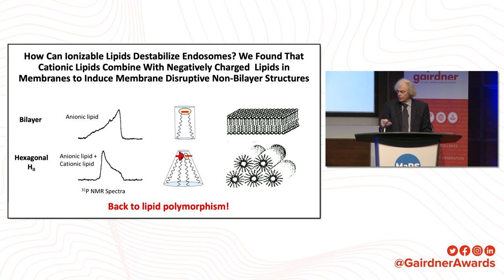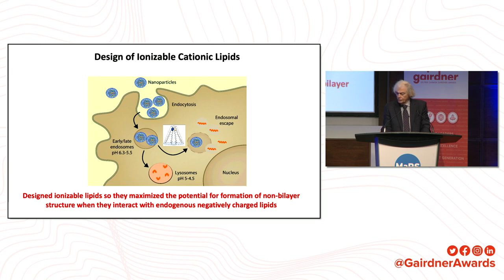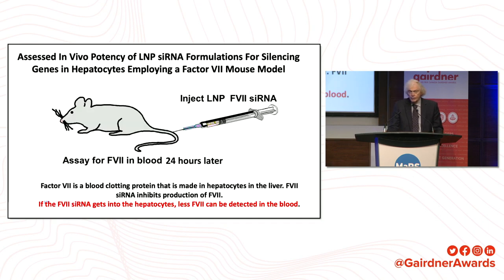And so this gave us a kind of design approach to go after the ionizable lipids, that at some point they become positively charged, and then destabilize the endosomal membrane. So that's the way. This was a design feature that we followed during this. We're still following it today, but during that collaboration with Alnylam for sure. So, engendering the maximized potential for formation of non-bilayer structures when they become positively charged. Now we assessed